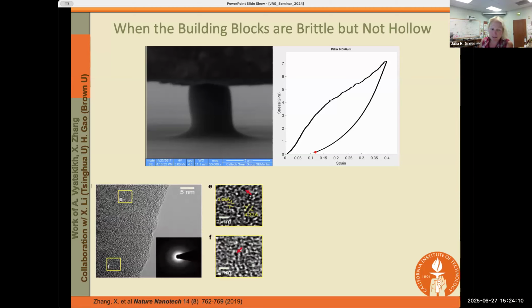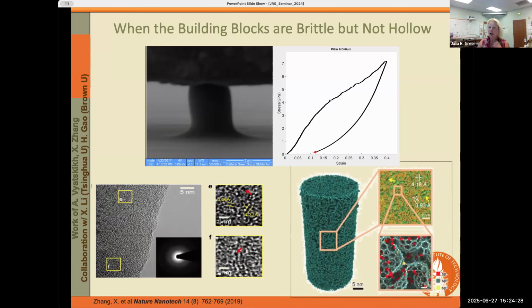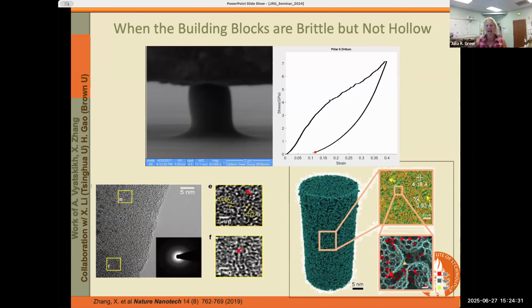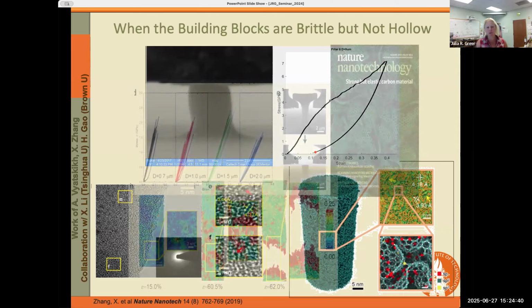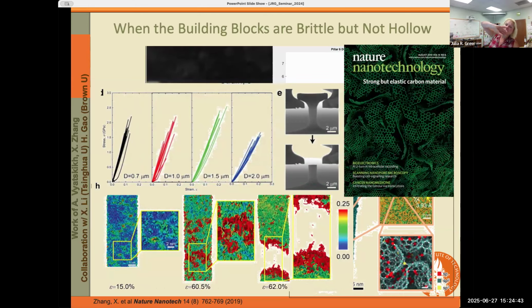So when we perform the microstructural analysis in the TEM, what we're observing is that what gives rise to this recoverability is the presence of graphene-like curved fragments that are sp2 hybridized carbon, effectively, and the local transformations within these localized regions are able to accommodate the globally applied axial strain. And so we collaborated with a group at Tsinghua University that were able to model using MD simulations the same kind of microstructure. And sure enough, what they showed is that it's the coalescence of these so-called hotspots within the pillar structure that allows these localized deformations to accommodate the global straining.